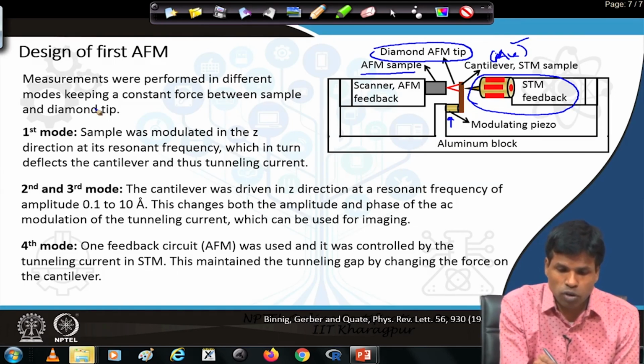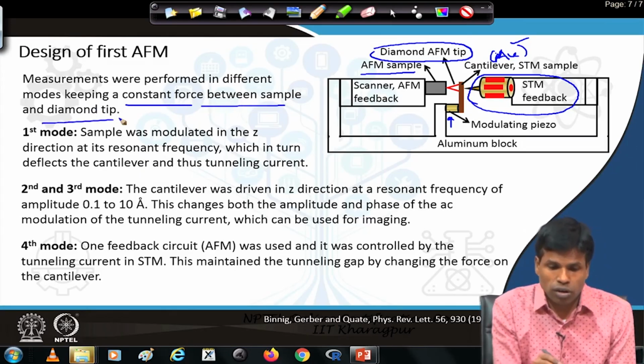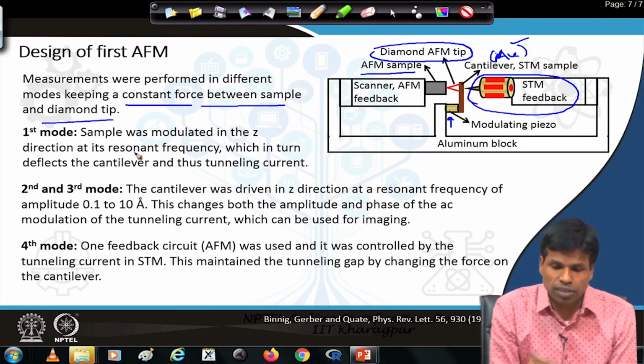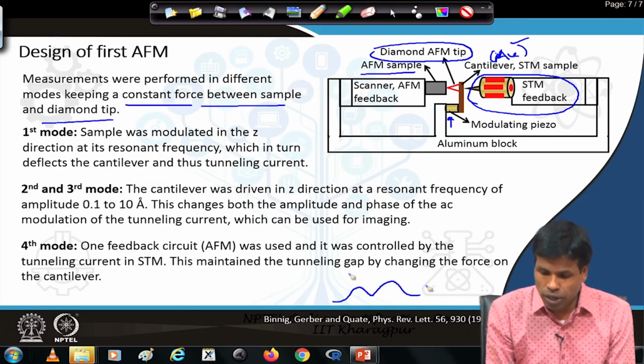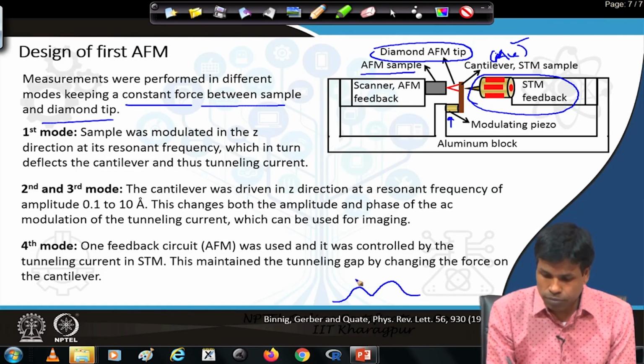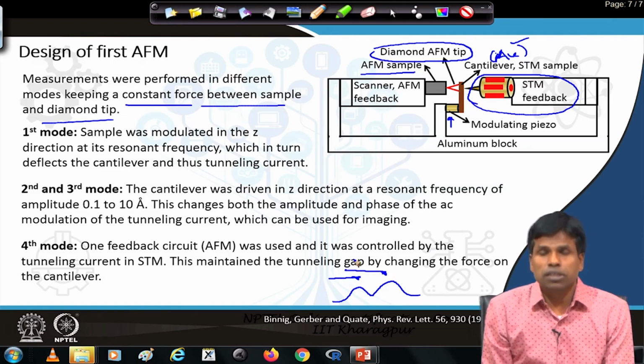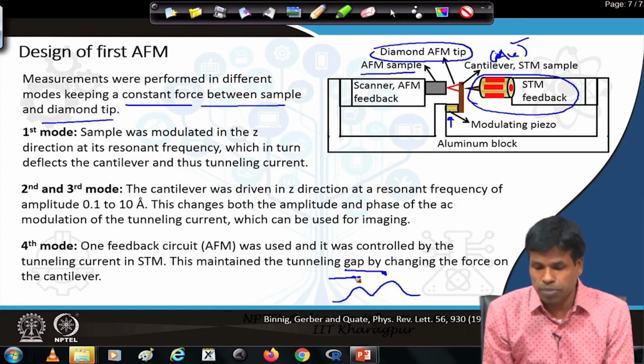In the first 1 to 3 modes, they kept a constant force between the sample and the diamond tip. The sample was modulated in the z direction at its resonant frequency, which in turn deflects the cantilever and changes the tunneling current. For example, our sample is like this, and our diamond tip with cantilever is moving above the sample. In order to measure the constant force between the tip and sample, the cantilever has to bend upward or downward, because the constant force will only occur when there is the same distance between the sample and tip.